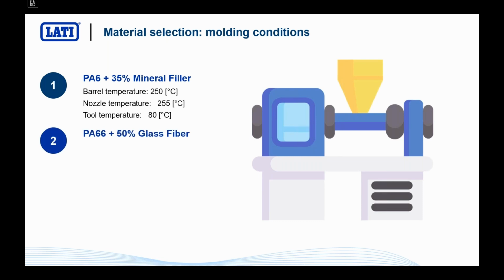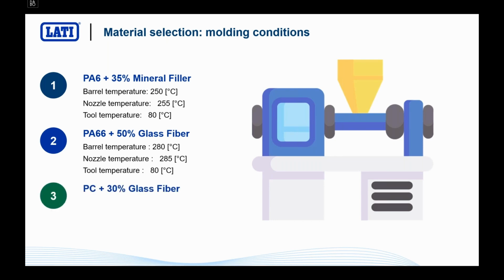Then we have polyamide 6,6, 50% glass fiber. In this case, the molding conditions are exactly the same that we use on this kind of polyamide 6,6. So 280, 285 for the barrel and the nozzle, and a tool temperature of 80 degrees C. For polycarbonate, we wanted to keep a bit open when it comes to the tool temperature for a reason that we are going to find out during the last design of experiment. All the rest is typical. This is the typical setup for amorphous polycarbonate.